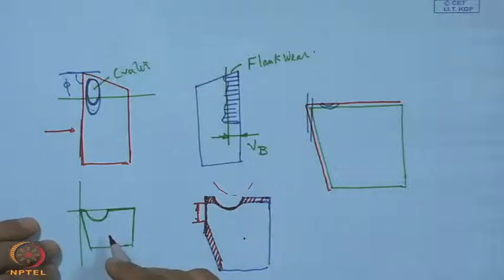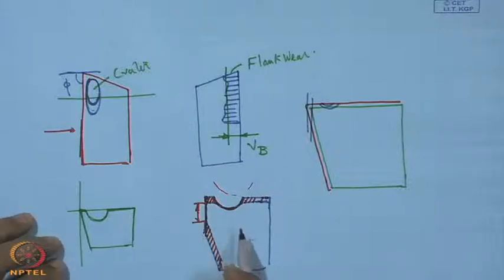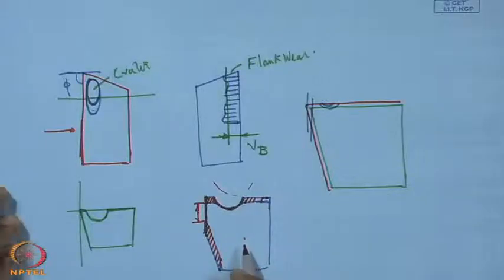Now, what is important here is that this test for wear should also be conducted, and it is very important, particularly in high speed operation. In that case, it is not the question of force or chip thickness, but it comes out to be the wear on the cutting tool, which changes its geometry position from the contact surface with the job, and because of the high rate, as the tool moves along the axis of the job, because of the wear rate on the tool, there could be a shortfall in the depth of cut, which may lead to a taper turning.